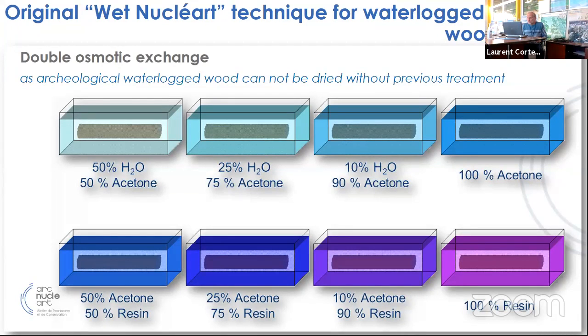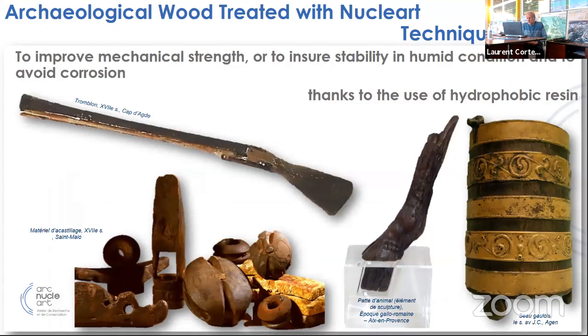It will collapse. So we propose and we do a kind of double exchange, double osmotic exchange, because resin cannot mix with water. So we use several baths to exchange water with intermediate acetone, and then to exchange again acetone to resin. It takes a long time, but it is very efficient. The volume of the artifact is very well conserved, and it improves a lot the mechanical strength, and it ensures a very good stability in humid condition.